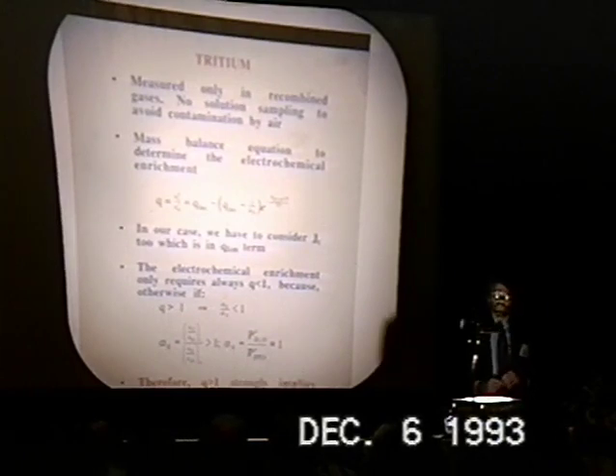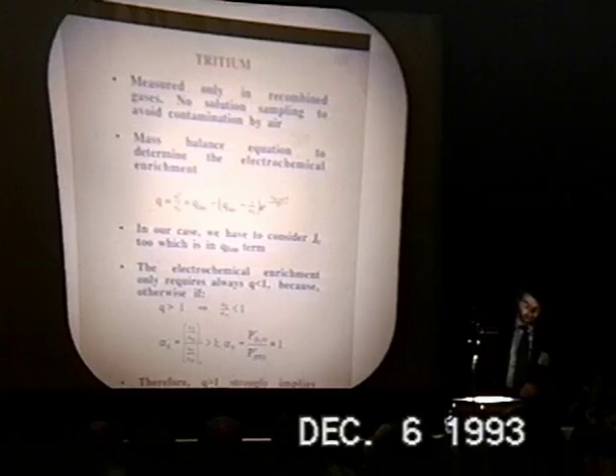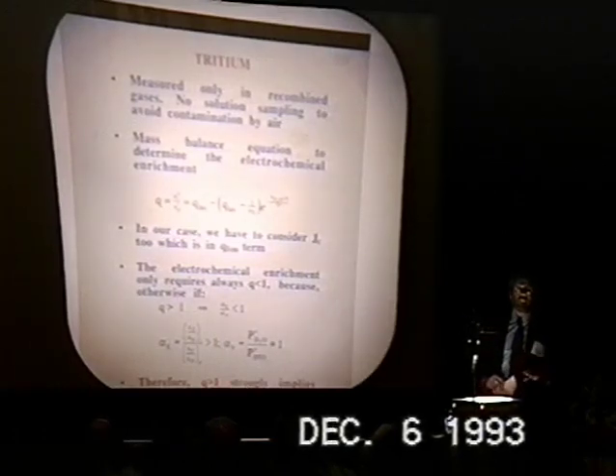Go to tritium. To avoid air contamination, we made tritium measurements only in a recombined gas, not in solution. The equation to estimate the electrolytic enrichment is this, and we define this quantity Q, which is given by the ratio between the tritium atomic fraction in gas phase and the initial atomic fraction in solution. So we have this equation, which is very similar to the equation found in literature, and this is put in a different form because we correctly have the dependence on the heavy water consumption, which is a function of the current, because in our experiment the current is not constant.